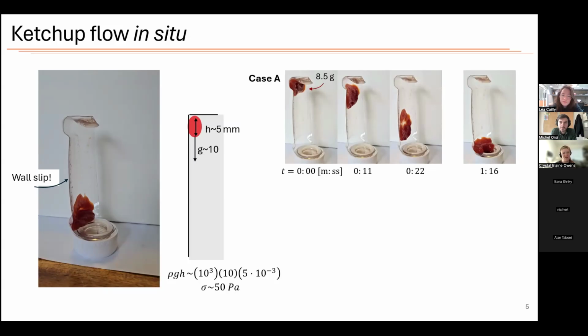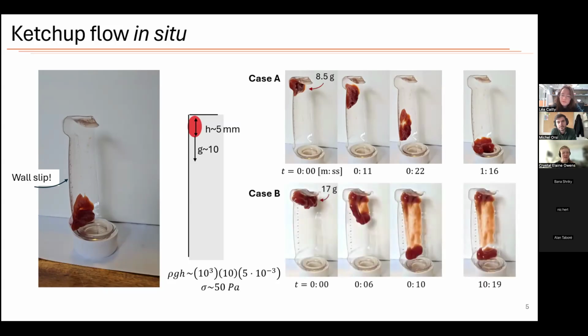So if we're thinking about the time of 5.7 seconds, we're definitely slower than that because it takes longer than that for the ketchup to even noticeably start flowing. In another case, if we start with a lot more ketchup, we see other effects where the ketchup almost immediately starts falling down, but it ends up leaving a streak that stays even after 10 minutes.